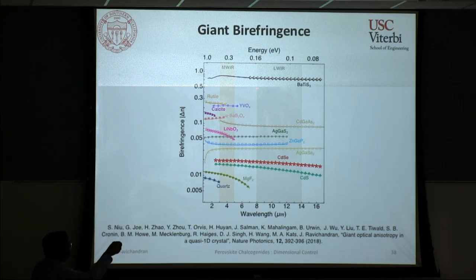So we picked most of the birefringent materials that are reported in the literature and are well known and commercially used, and we compared them with our material, and we found that over the whole energy range of interest, this was at least 3 times larger than the next highest birefringent material that we knew. Not only that, this has almost 10 times larger birefringence in the mid-wave and long-wave IR region, where almost no birefringent material currently exists of any appreciable value.